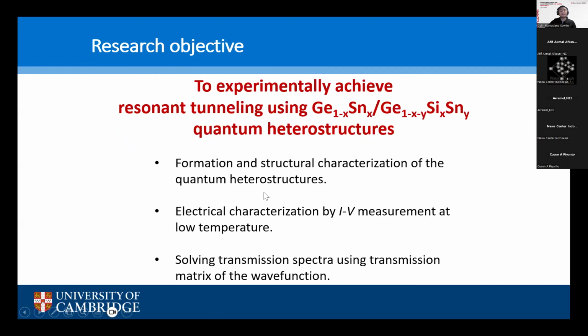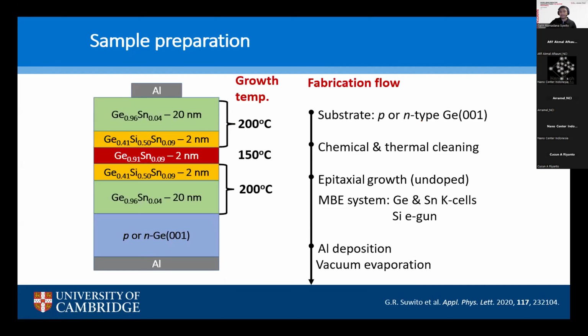Okay, so our research objective was to experimentally achieve resonant tunneling using germanium tin based quantum heterostructures. For this purpose, we prepared quantum heterostructures by molecular beam epitaxy. And in our case, we sandwiched a germanium tin well, colored red in here, with two germanium silicon tin barrier layers here.